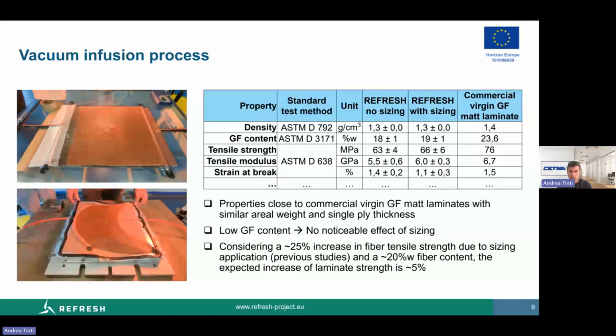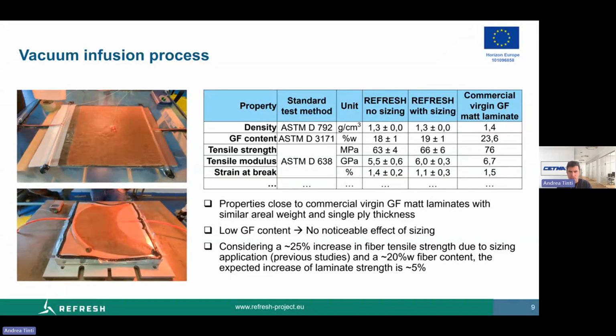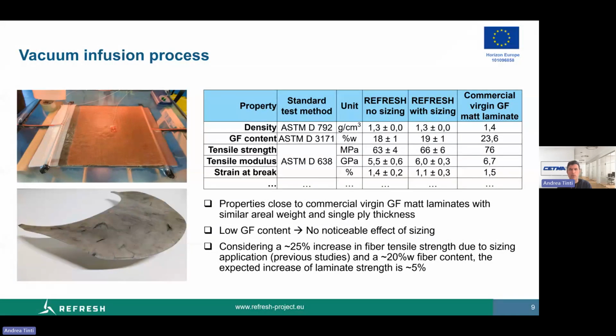As a matter of fact, in this case no significant effect of the sizing was noticeable, but it was probably due to the low glass fiber content in the laminate, which, as you can see, was below 20%. So the expected increase of laminate strength is within the range of the properties' standard deviation.